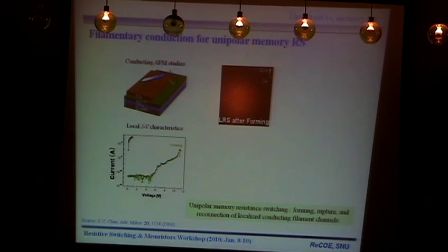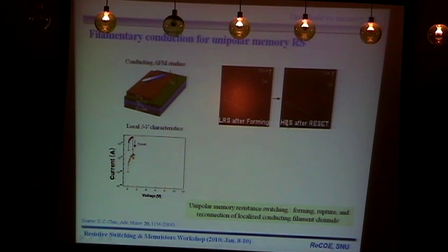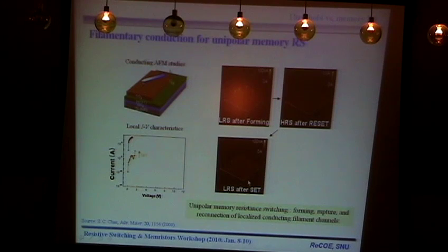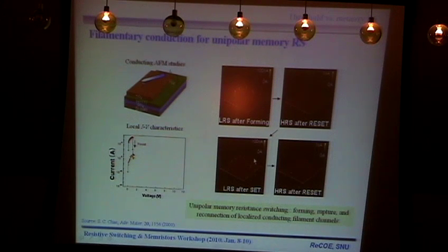First, it is in the insulating state. Then, if you increase your voltage, it will make a forming, and then it enters the low resistance state. When we scan through, we found that there is a certain spot which has a very low resistance, so there should be a conducting channel below. Then, when we make a reset process, entering the high resistance state, all these channels disappear. Then going back to the low resistance state, the channel appears again, and disappears, and so on. This all indicates that unipolar memory resistance switching should come from the forming, rupturing and reconnection of these localized conducting filament channels.